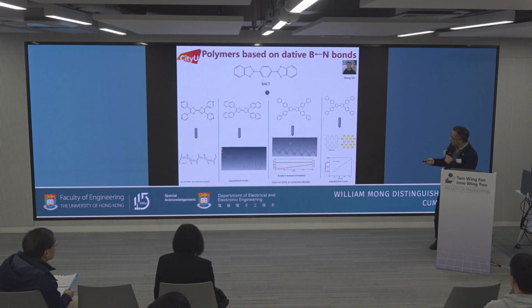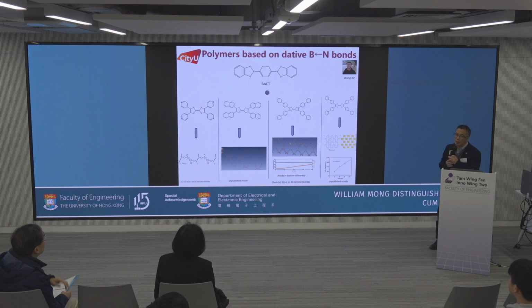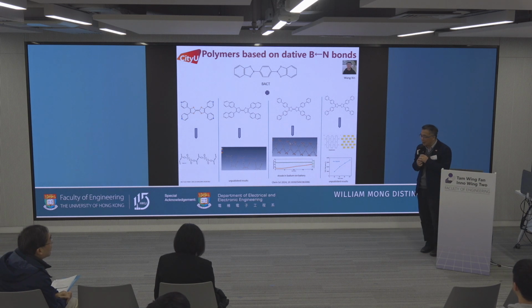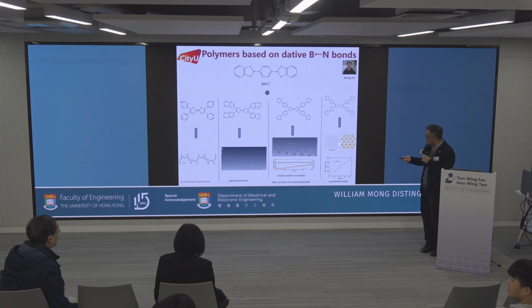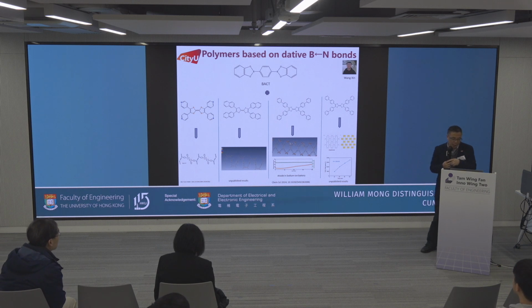Okay. And what happens if you move the nitrogen from the 4 position to the 3 position? It turns out the coordination will change, and this can form a 2-dimensional structure, as shown here. And TTF is also very good as a catalytic unit. We can use this for hydrogen peroxide evolution. We just finished this result, and this paper is still in preparation, and hopefully we can submit this paper in January or February.